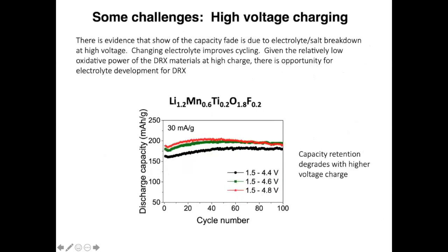So I want to end with some of the challenges for these materials. Because these materials have more of a voltage slope than layered materials, you'd like to go to high voltage to charge them. And that definitely degrades cyclability. So here's a manganese titanium system. If we charge to 4.4 volt, capacity increases a bit in the beginning, and then it's fairly flat. When you increase the charging voltage to 4.6 or even 4.8, you get higher capacity, but you also see that the capacity fade is a little higher.